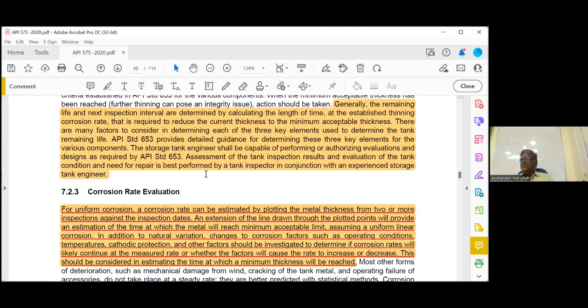Suppose if you know the corrosion rate, you can make a plot. There is a graph given, and find out what will be the thickness after 5 years also. Okay. For uniform corrosion, highlight this one. A corrosion rate can be estimated by plotting the metal thickness from 2 or more inspections against the inspection dates. An extension of the line drawn through the plotted points will provide an estimation of the date at which the metal will reach the minimum acceptable limit, assuming a uniform linear corrosion.